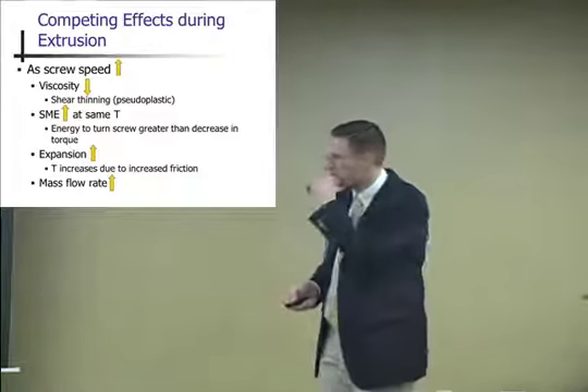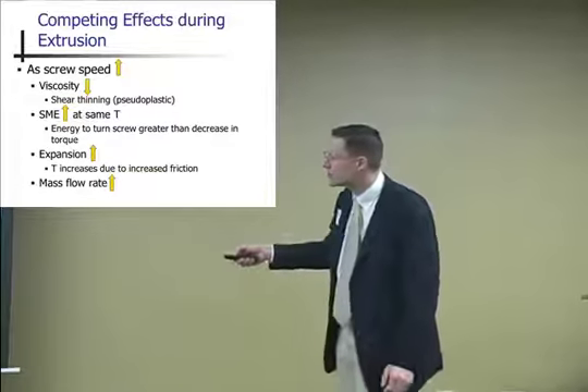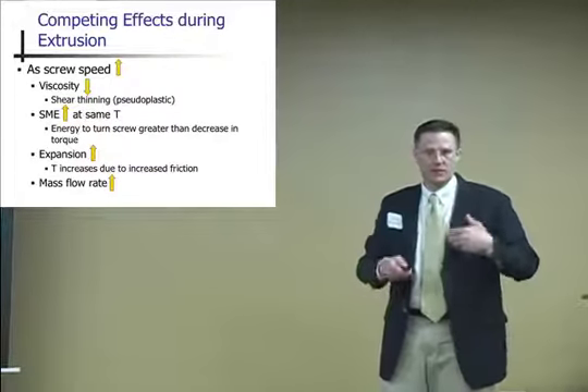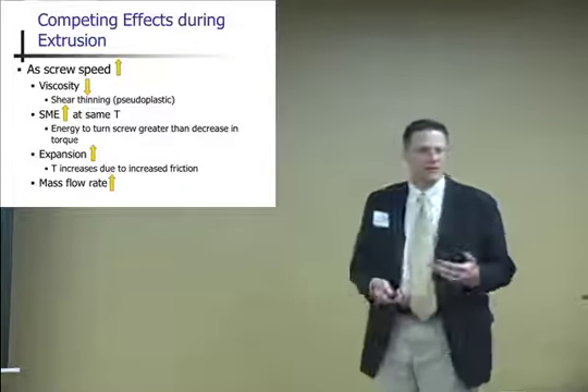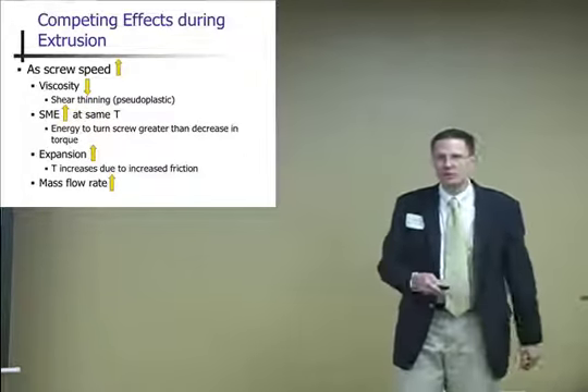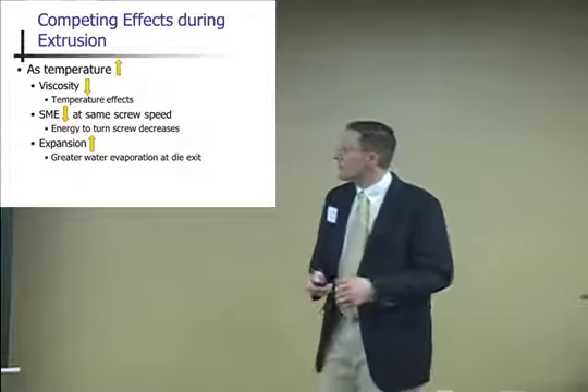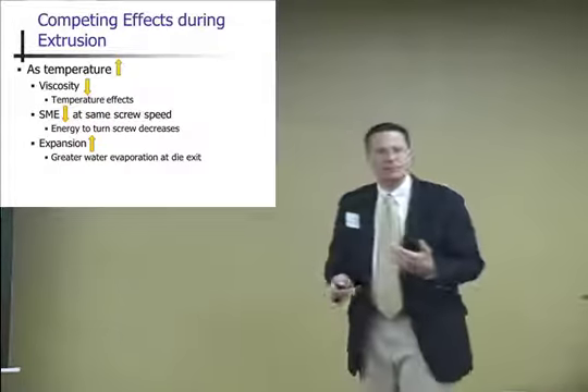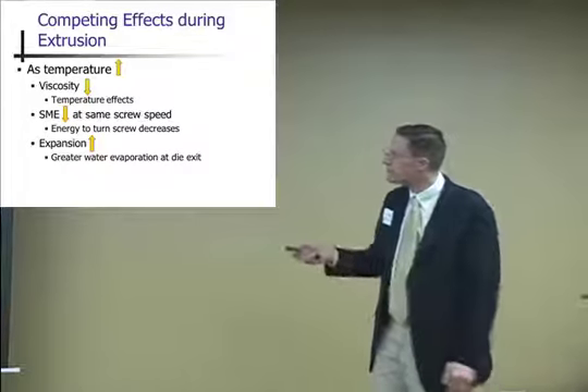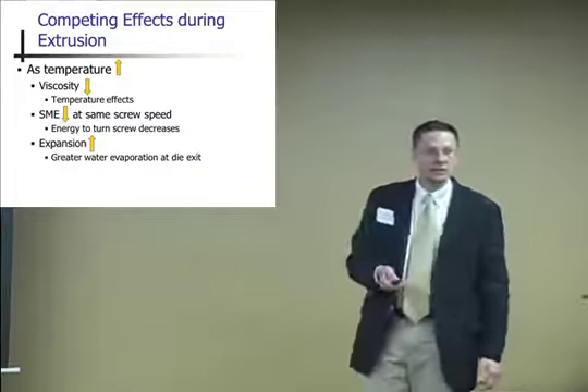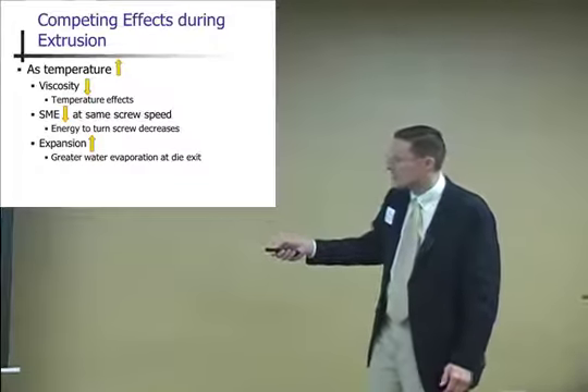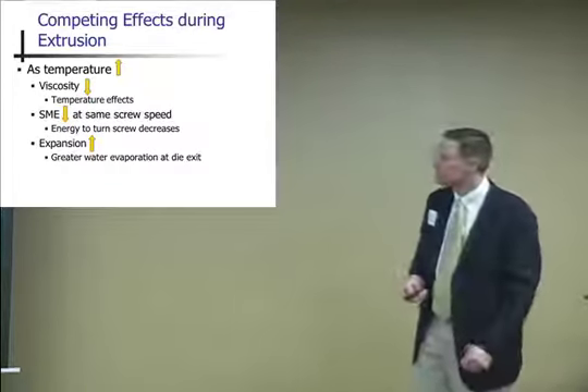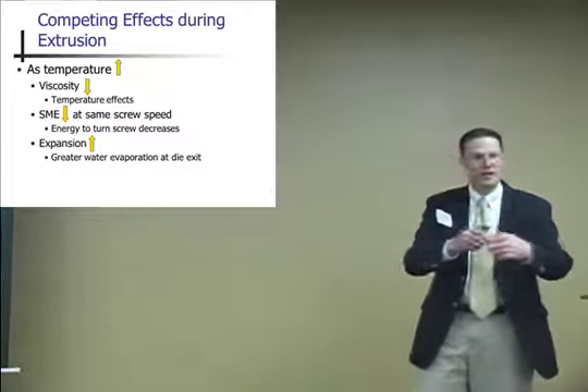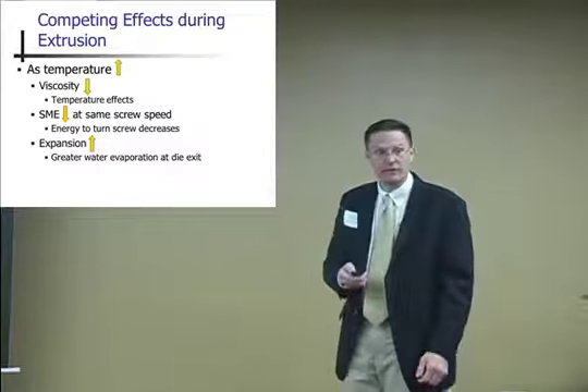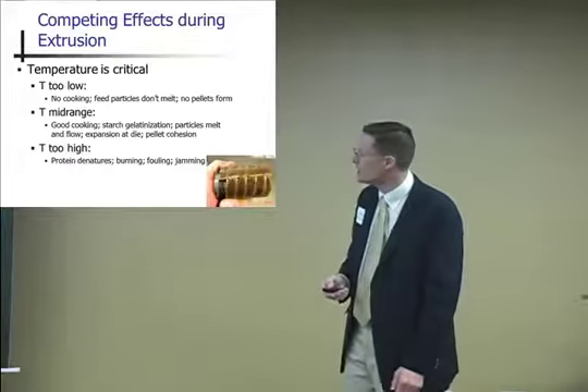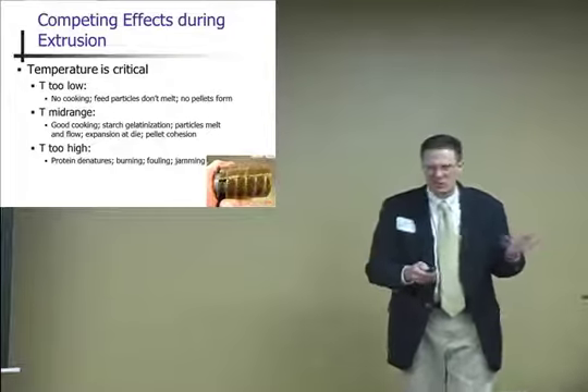Now, I say should because this isn't always true, but your expansion should increase because of the increase in temperature, because of the increase in friction. And of course, the faster you turn the screw, the faster you should have throughput through your extruder. So, keeping everything else constant. As you increase the temperature, if you have band heaters or you're adding steam, viscosity should go down as temperature increases. Your SME should go down at the same screw speed because your viscosity is going down. Your expansion should go up because you have faster, greater water evaporation at the die exit. So temperature is critical. Water is critical, but so is temperature.